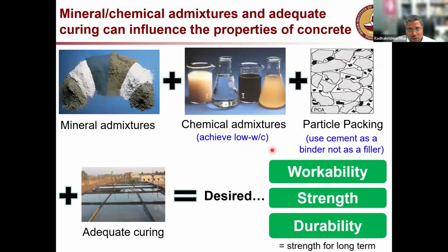Now, to also make good quality concrete, what we do is put in mineral admixtures and chemical admixtures, and we try to minimize the amount of cement. When you talk about good quality concrete, this is something very important. Usually people will say add more cement and make the concrete better. It is not like that. We have to increase the amount of aggregates, or sand or coarse aggregate and fine aggregate, in the concrete and minimize the amount of cement. That will be a better quality concrete.